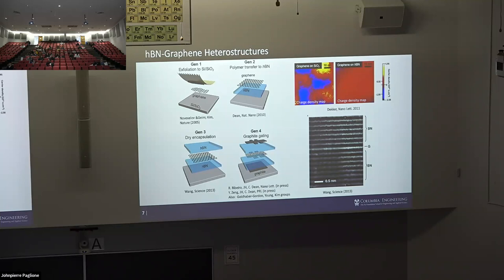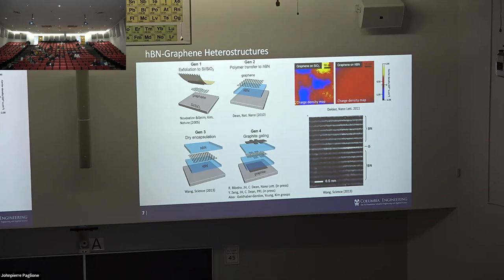This is incredibly surprising given that all of this is done in air on a desktop. Anything exposed to air is instantly covered in some kind of junk — aromatic hydrocarbons will instantly stick to graphene. What happens at these very low friction interfaces is that when graphene and boron nitride are brought together, contamination is squeezed out. These are magically self-cleaning interfaces. The contamination forms bubbles that we have to work around, and at Columbia we're working on techniques to keep improving that process.